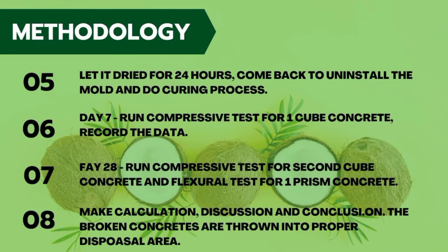For the fifth step, we let the cement mixture in the mold dry for 24 hours, then came back the next day to remove the mold. After that, we performed the curing process by placing the concrete into a tub with water. On day 7, we removed the concrete from the tub, then ran the compressive test on one cube of concrete and recorded the data. On day 28, we ran the compressive test on the second cube of concrete, and for the prism concrete, we conducted the flexural test.